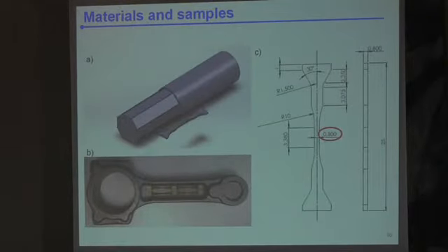And in the bulk, of course, the grain size remains intact. Samples. So we are going to look at the cracks in 3D using X-ray tomography, synchrotron X-ray tomography. So we unfortunately have to deal with small samples. Small is from roughly a cross-section of 1 by 1. This is slightly under 1, it's 800 micron. It's not a big issue in the sense that we want to deal with short cracks, right? We want to know how they behave when they are sub-millimetric or 500 micron.